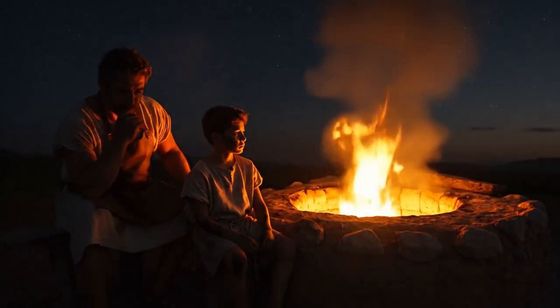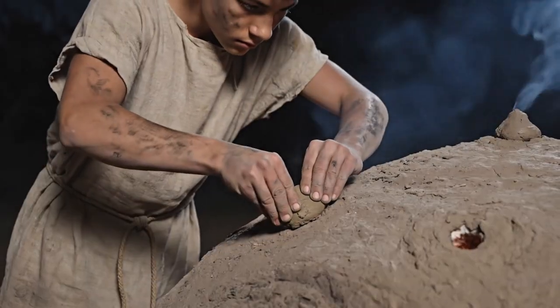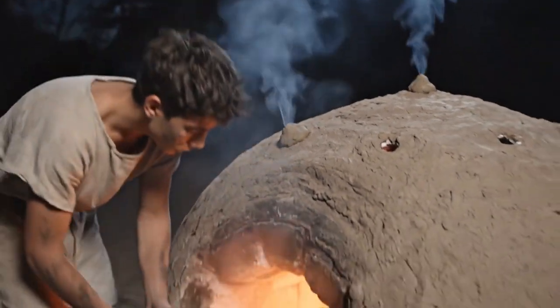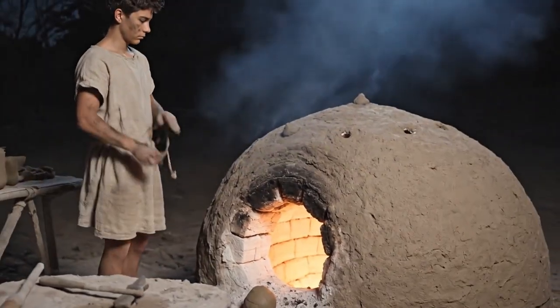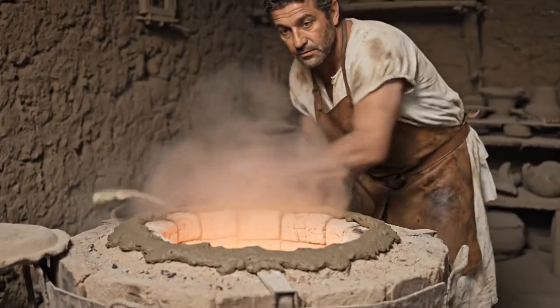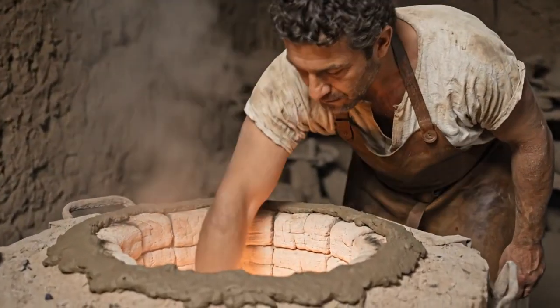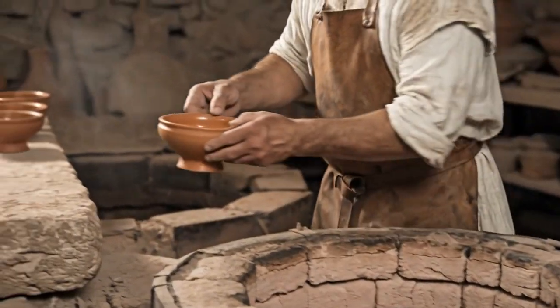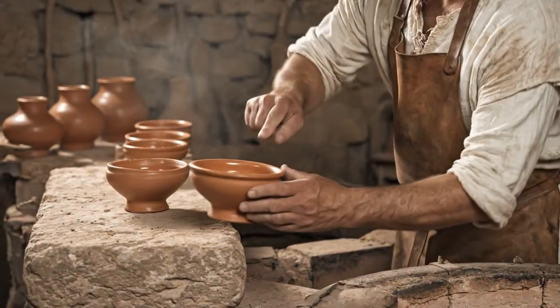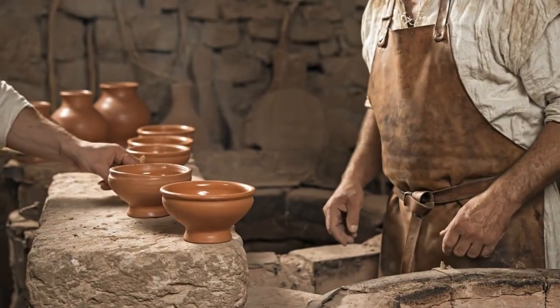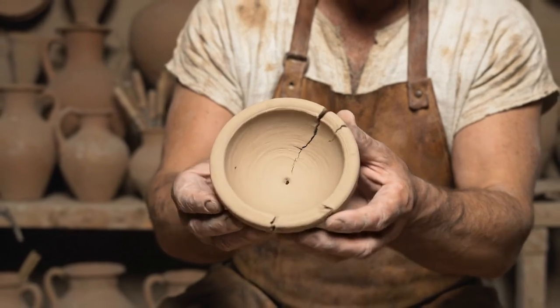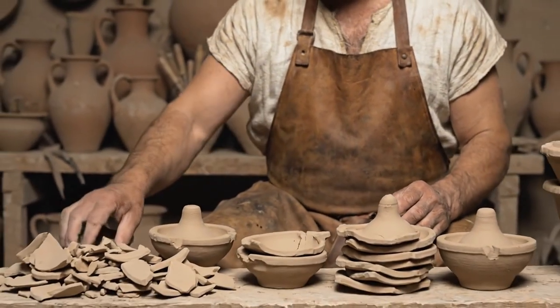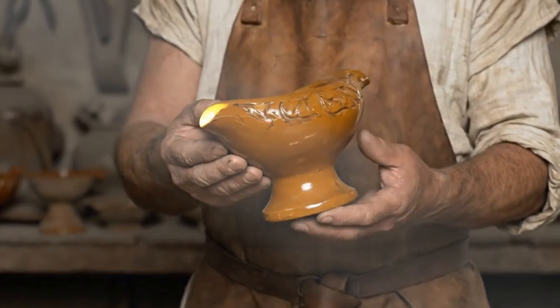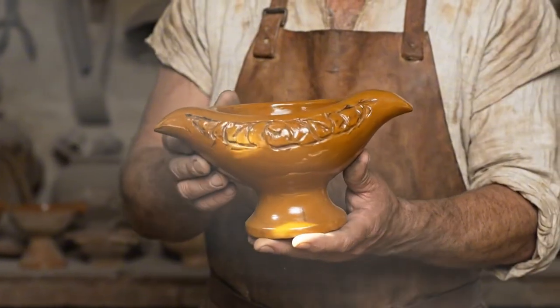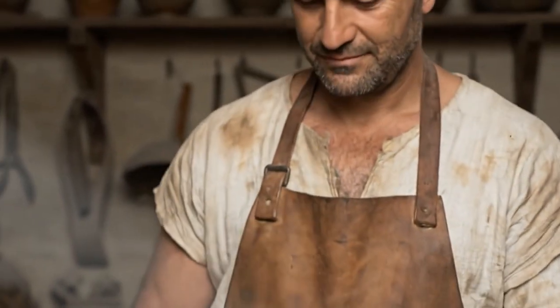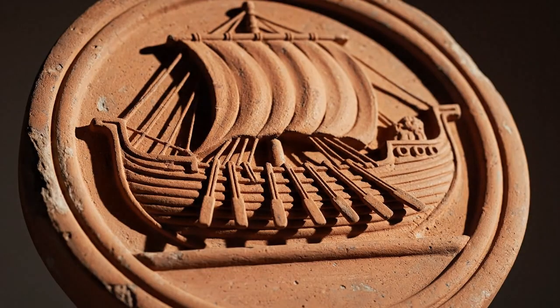The entire firing cycle, from first flame to final cooling, can take up to 2 full days. A day of heating and a day of slow, patient cooling, with the kiln sealed to prevent thermal shock from cracking the finished wares. When the kiln is finally opened, the potter reaches into residual warmth and withdraws the lamps one by one. Each is inspected. Cracked lamps, casualties of uneven drying, air bubbles, or temperature gradients within the kiln are discarded as wasters. Archaeologists have found these rejects at production sites, invaluable evidence of workshop location and quality standards. Successful lamps emerge transformed, hard, resonant when tapped.